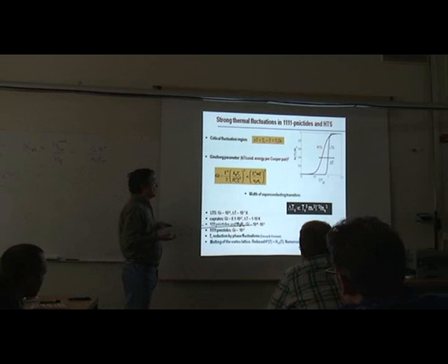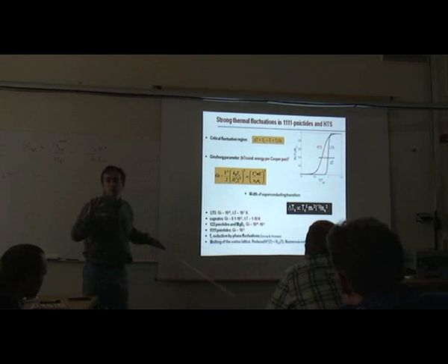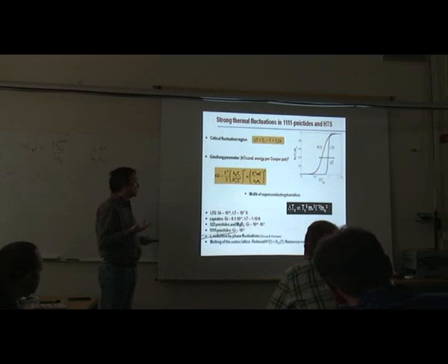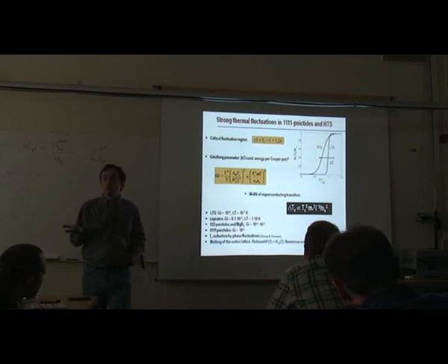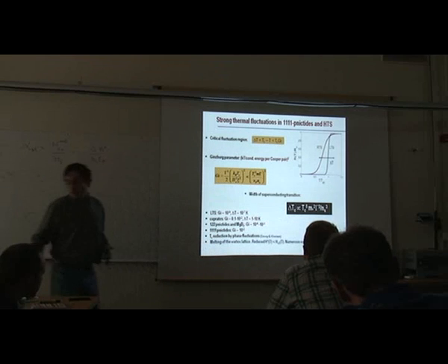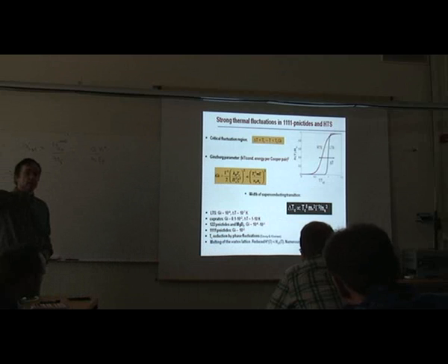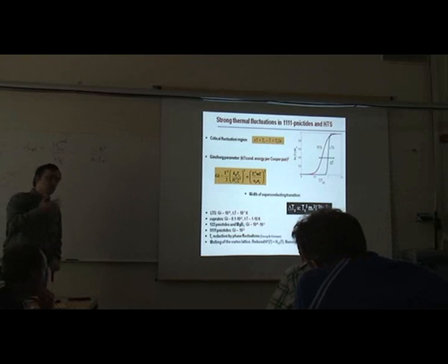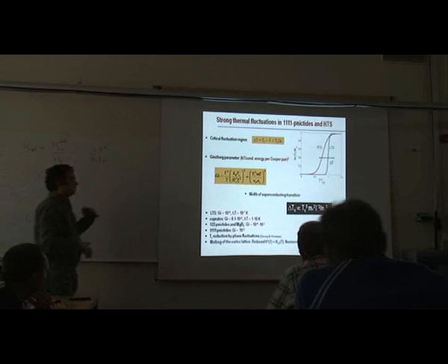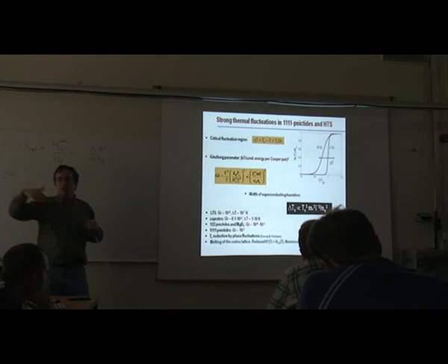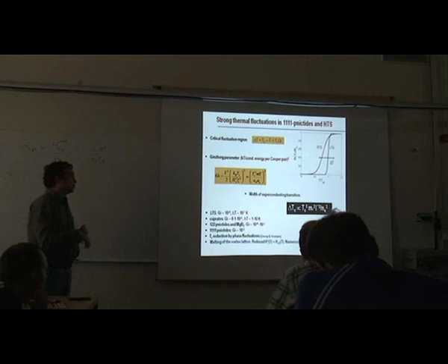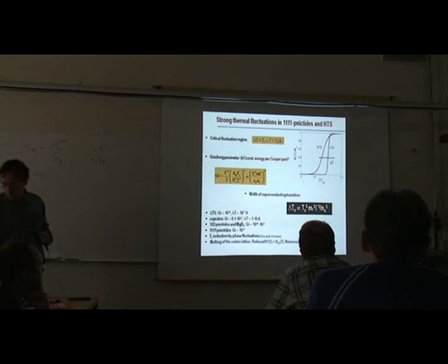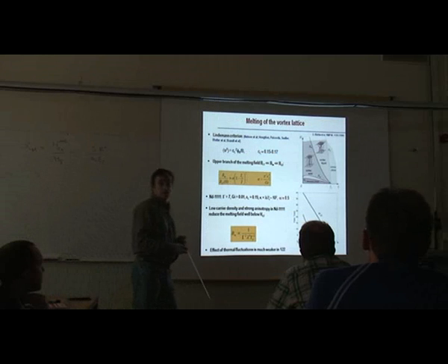The 122 pnictides have a Ginzburg number similar to MgB2, kind of an intermediate state. The 1111 pnictide, which has the highest Tc, has a Ginzburg number the same as YBCO, the cuprate. It's simply because of that. So you can actually model all the behavior from classical low Tc vortex dynamics, let's say in this cuprate, and then you can go to the high temperature, to the effects expected from high Tc cuprates for the 1111 compound, and one manifestation of that is vortex melting.